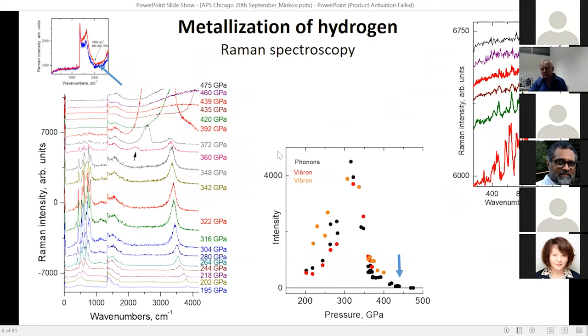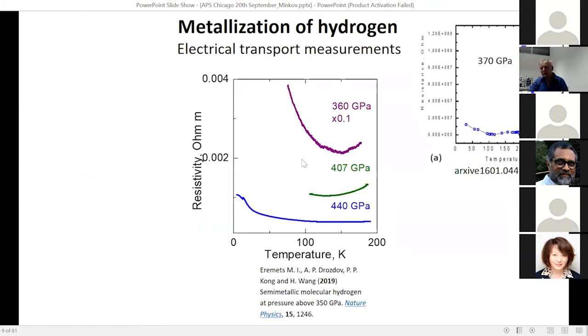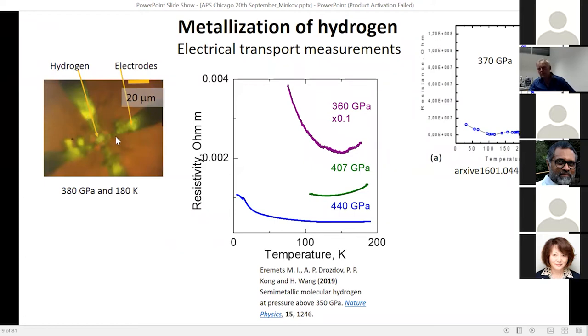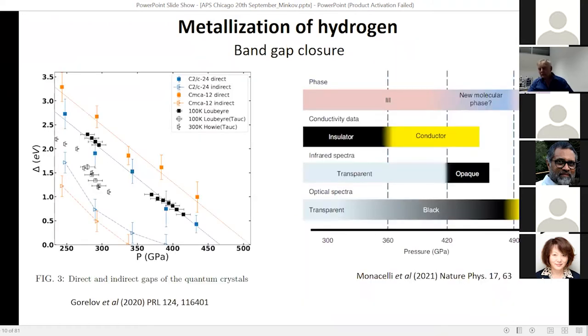We measured properties of hydrogen up to nearly five megabars and performed electrical measurements of hydrogen. We placed a hydrogen sample with four electrical leads and observed a funny temperature dependence of resistance, confirming that hydrogen transforms to a metal in a particular way due to band gap closing — around 350 GPa, consistent with recent theoretical calculations.